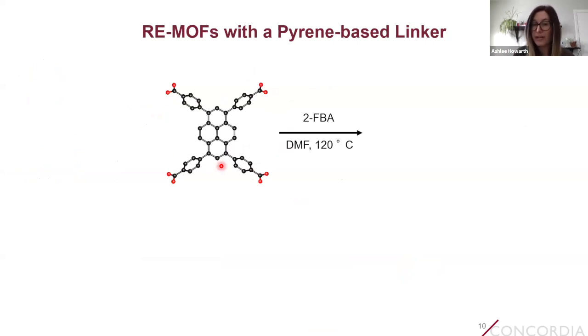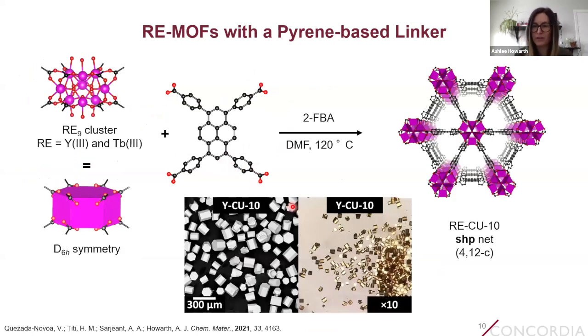So using a fluorinated modulator, also in DMF at 120 degrees Celsius. And from that, he was able to make the new material rare earth CU10, which has these 12 connected nonanuclear cluster building units, which give rise to the double 6-membered ring that's required to generate that SHP topology. And he originally made this MOF with yttrium and terbium.